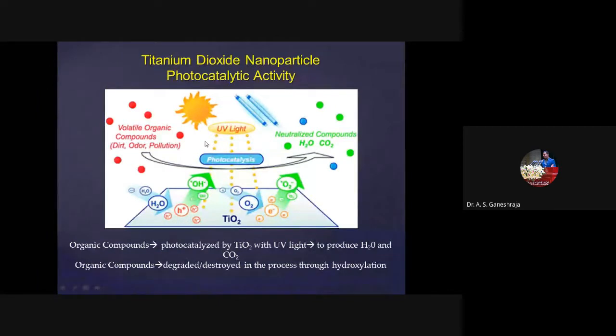This is the photocatalytic activity of titanium dioxide nanoparticles. Titanium dioxide nanoparticles have a valence band and a conduction band. When we irradiate with UV light, the electron goes to the conduction band. So these conduction band electrons react with atmospheric oxygen and convert it to superoxide radicals. These superoxide radicals are very active radicals. This active radical can react with other inorganic or organic materials and decompose them into carbon dioxide and water. So in this part, an oxidation reaction takes place. In this part, a reduction reaction takes place. So some volatile organic compounds can decompose in this process.